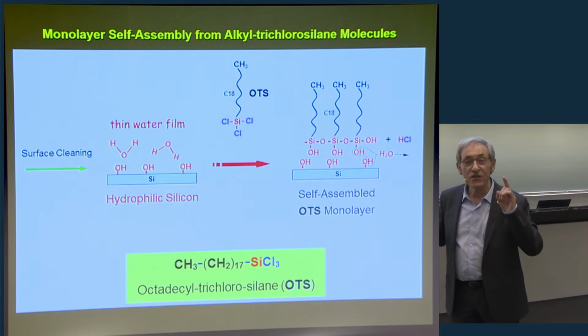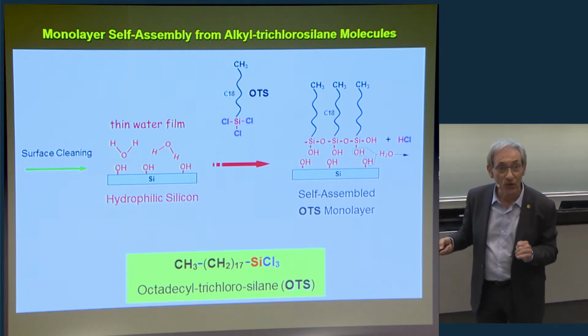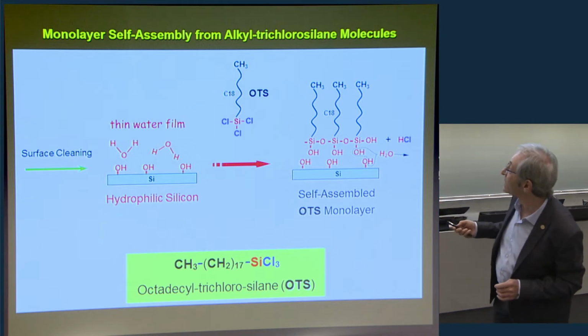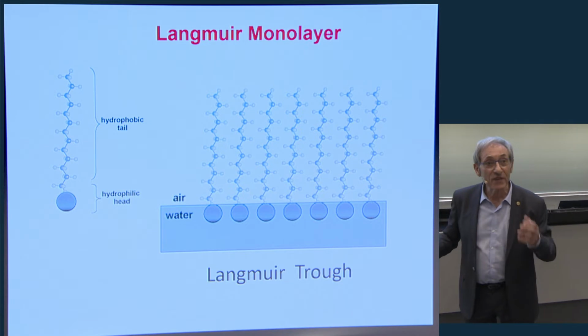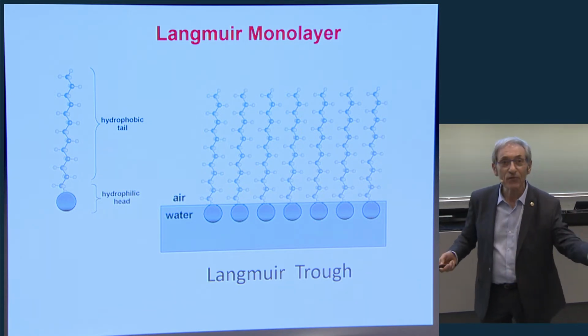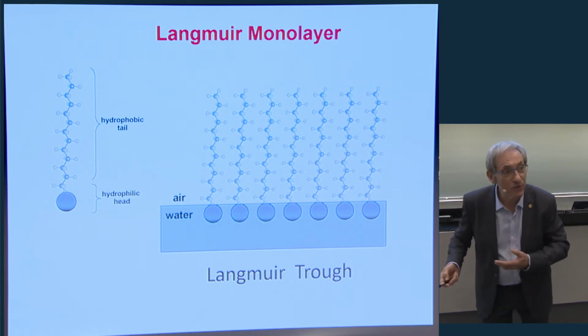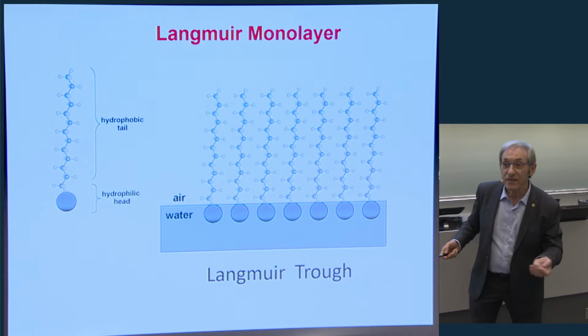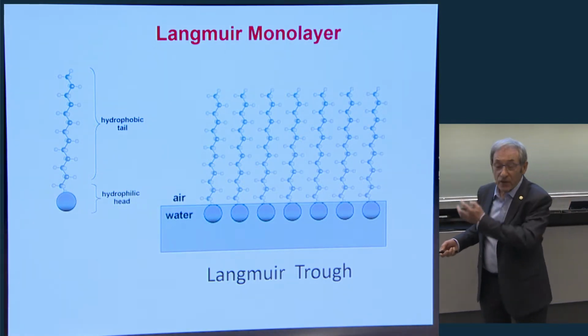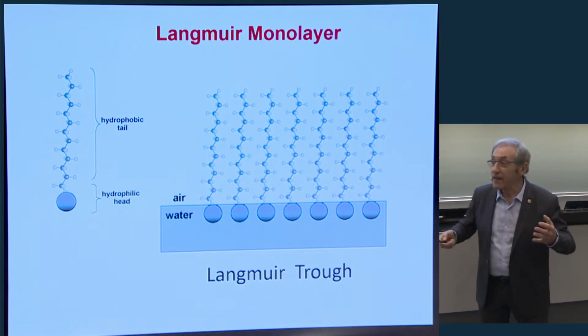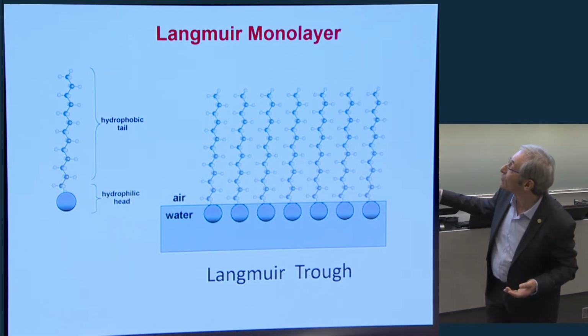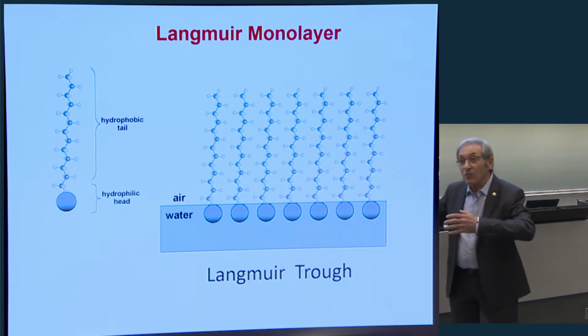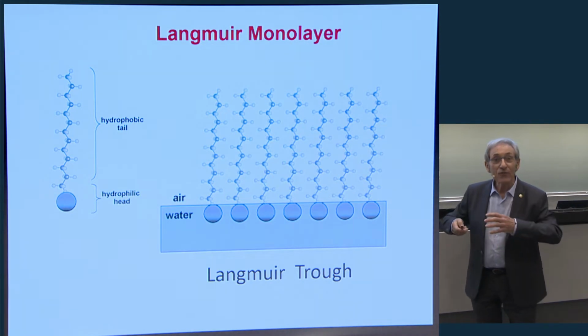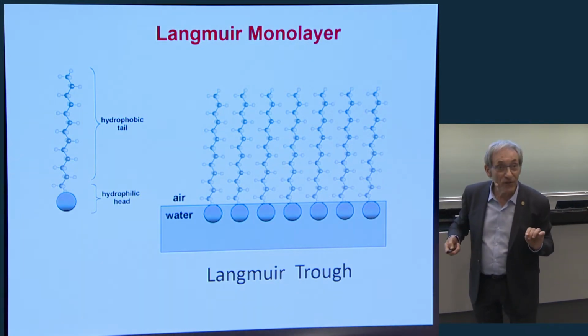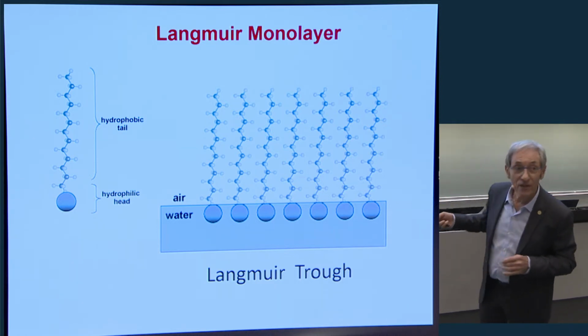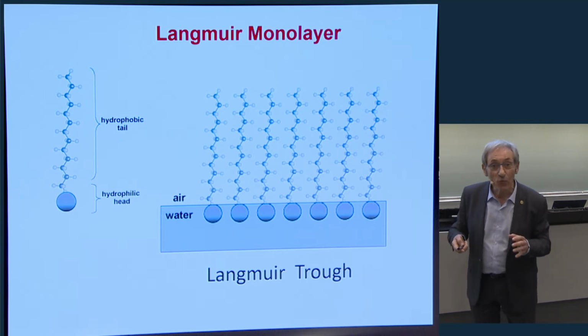I should stress, not each molecule has to bind to the surface, and this is very important. Actually, there is a lot of mobility here, and this is also a very important feature of these monolayers. This has to be distinguished, for example, from monolayers of the kind that we have just heard before, like thiols on gold, where the binding is to specific atoms on gold. Here we do not have a specific binding, so the monolayer is more or less like a Langmuir monolayer. This is a Langmuir monolayer floating on water. Our organosilane monolayers are formed on a very thin layer of water on the surface, so in this sense, they are similar to Langmuir monolayers. So there is a lot of lateral mobility.